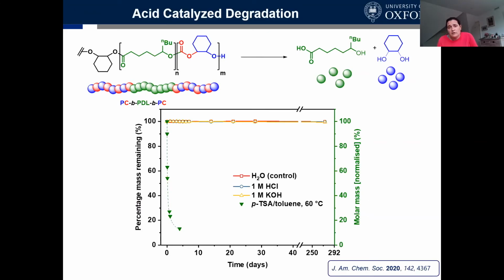The final point, which we opened with, was that ester chemistry and carbonate chemistry is closer to equilibrium. And here is a demonstration of that point, because if we just put the polymer into water, nothing happens over many days, over 290 days, everything is fine. And the same in weak acid or weak base. So that's important because our polymer needs to be able to be used. And we can't have something that hydrolyzes in a toughened plastic application just on a droplet of water.